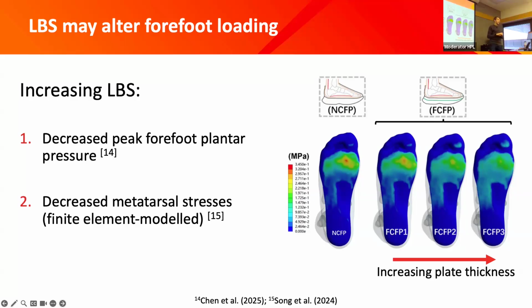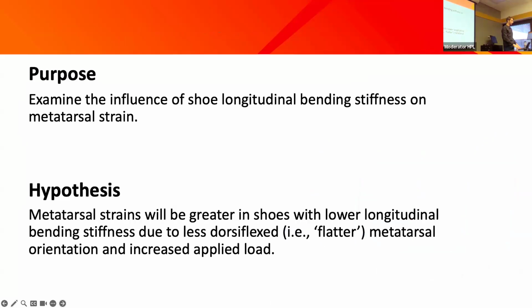In a second study, they took it one step further and modeled metatarsal stresses in different situations with a carbon fiber plate, and they showed that increasing the carbon fiber plate thickness decreased those metatarsal stresses. This is cool, but it's not actual experimental data, so it's still important to see what happens in the real world with these situations.